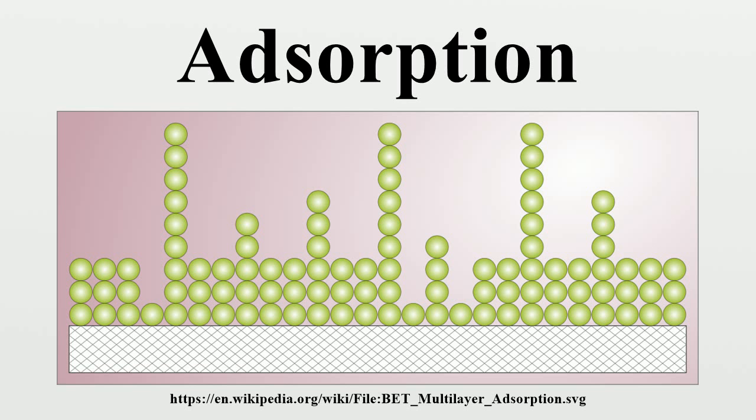Usually, if we call Vm the STP volume of adsorbate required to form a monolayer on the adsorbent, and we obtain an expression for a straight line through its slope and y-intercept, we can obtain Vmon and K, which are constants for each adsorbent-adsorbate pair at a given temperature. Vmon is related to the number of adsorption sites through the ideal gas law. If we assume that the number of sites is just the whole area of the solid divided into the cross-section of the adsorbate molecules, we can easily calculate the surface area of the adsorbent.